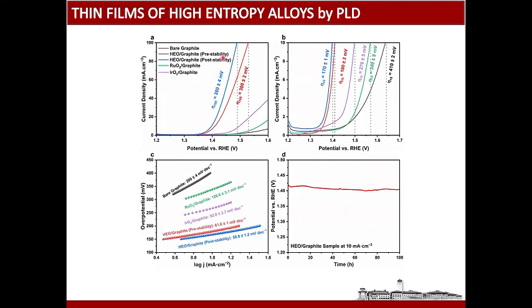And this is before the stability test, and after the stability test, it even decreases to 260 millivolts for the oxygen evolution reaction. And compared to the ruthenium and the iridium, it is much better. And the Tafel plots are also low compared to the iridium oxide and the ruthenium oxide samples, and it is again highly stable. Like you see, there is a 100-hour stability test here at 10 milliamps current density, and it is quite stable. Ruthenium and iridium oxide samples are not stable.